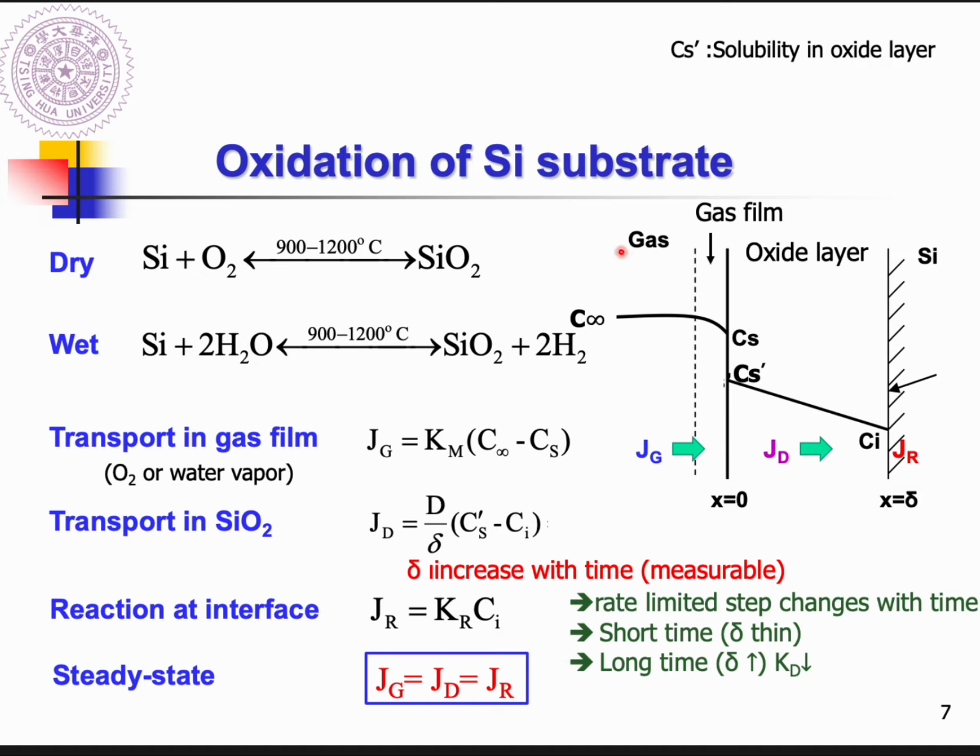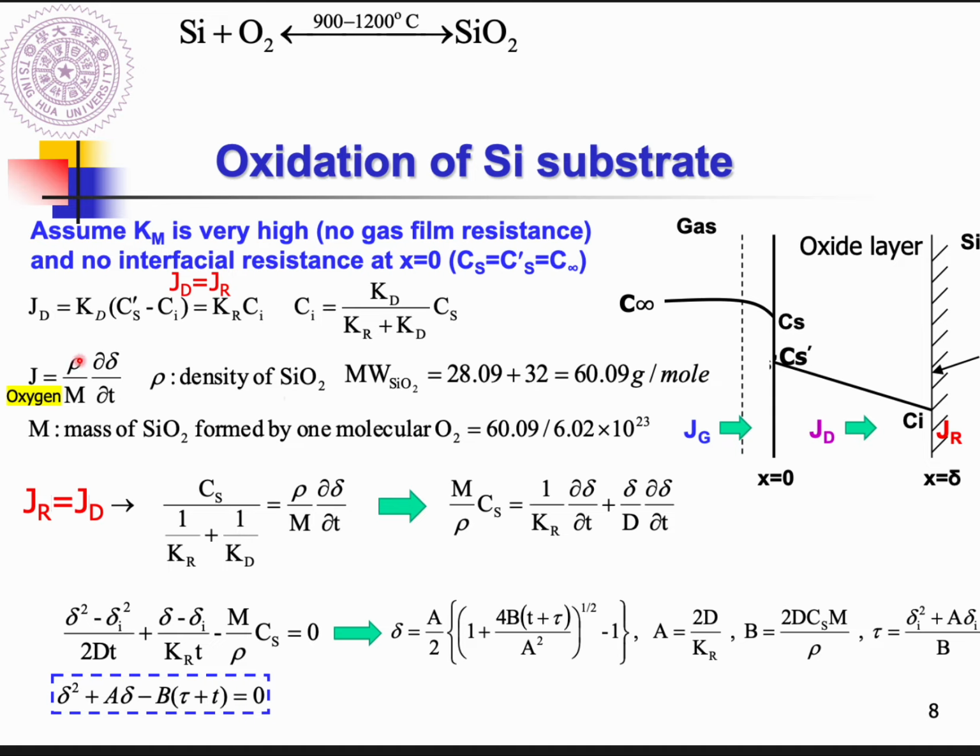The only difference is you substitute this gas with water vapor, and the rest of the part will be similar, right? But because it's water vapor, the concentration and the transport coefficient should be a little bit different. And also this part has already changed with the water vapor, so the ρ/M should be modified, okay? But most parts actually remain constant in that situation, okay?